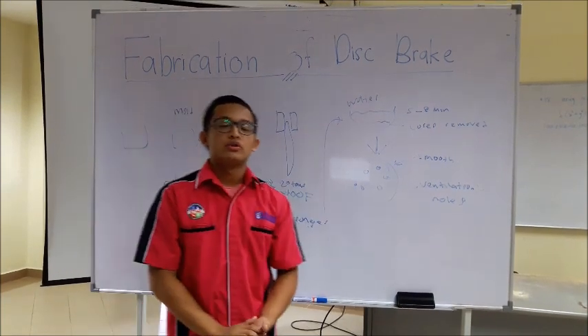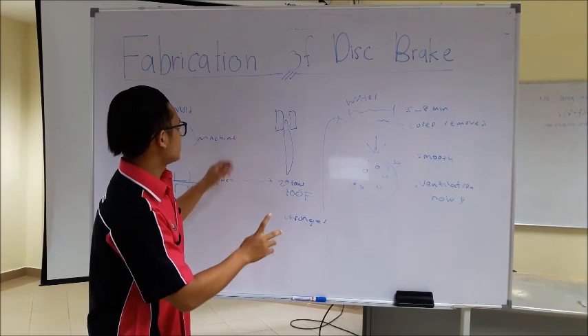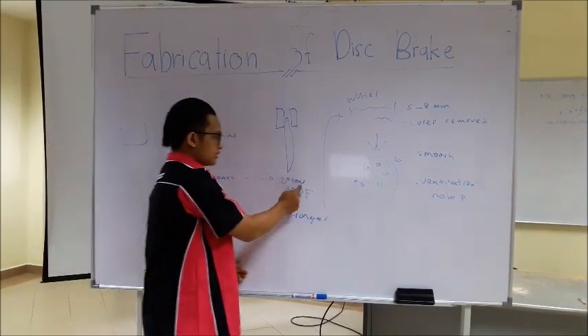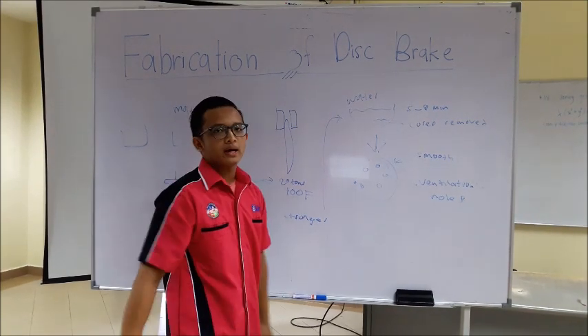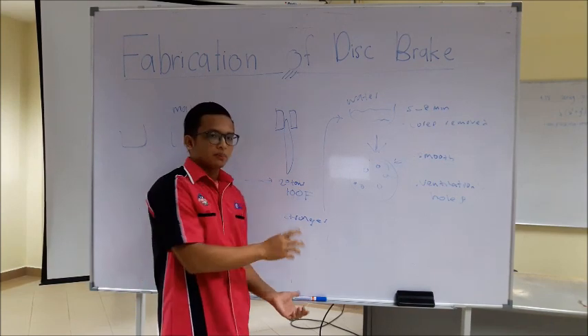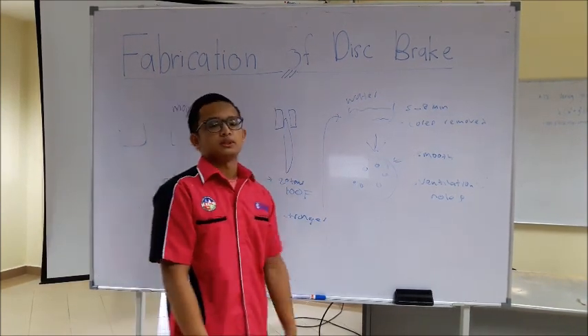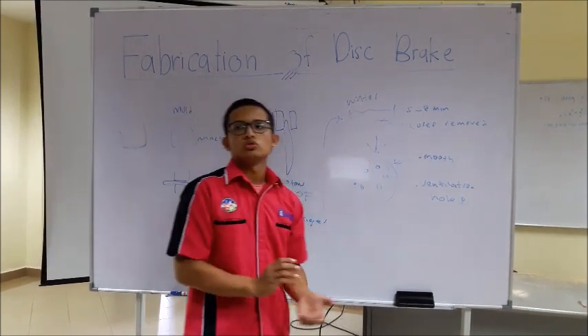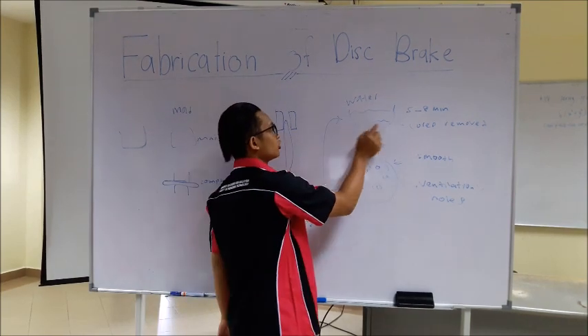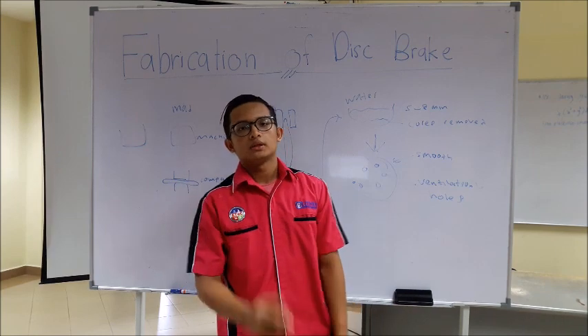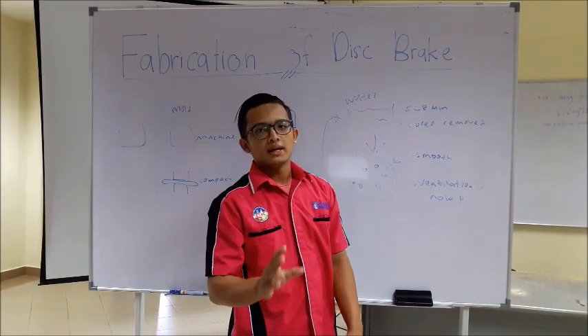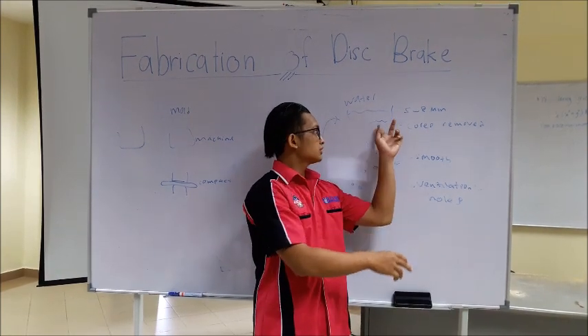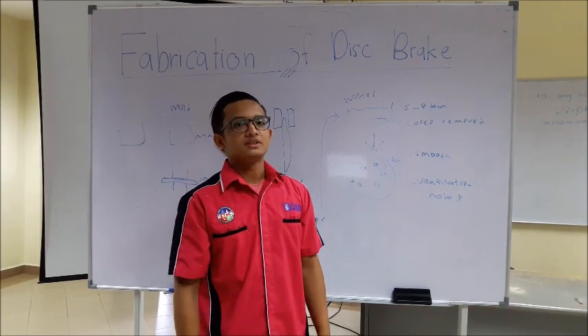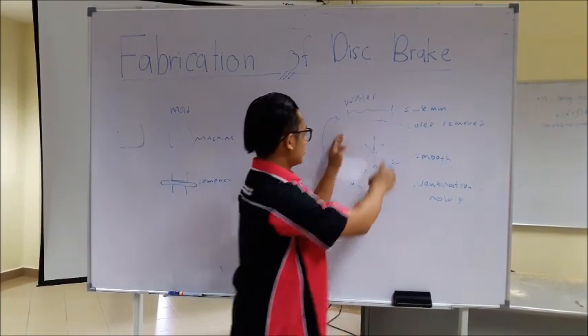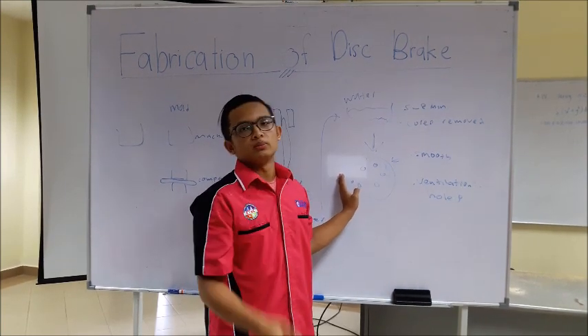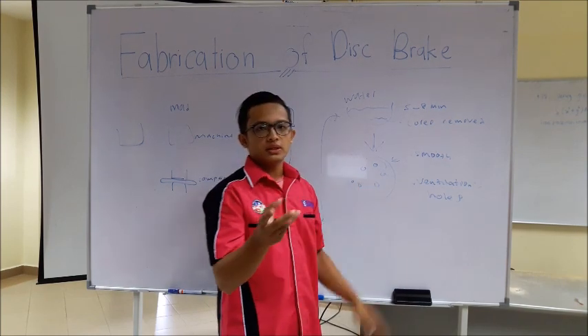Then the fully covered mold is sent to a last press, which applies 20 tons of pressure and heats to 400 Fahrenheit. This heat and pressure compact the carbon fiber and resin to make it stronger. Once the mold is cooled down enough to be handled, it is submerged in cold water for 5 to 8 minutes, which cools down the disc ring completely, enabling us to pull out the cores that were inserted for the ventilation holes. Once the cores have been removed, remove the cover of the mold and pull out this ring from the mold.